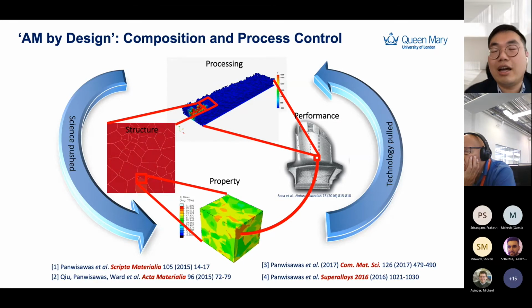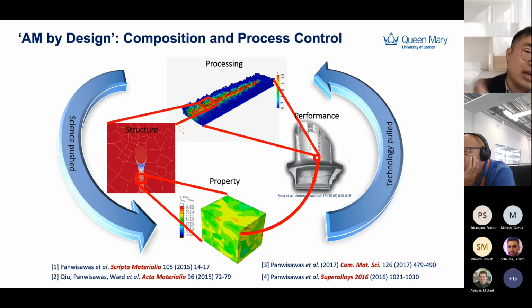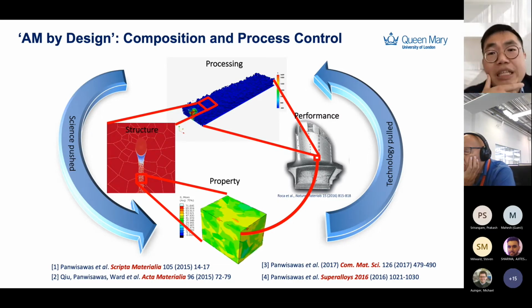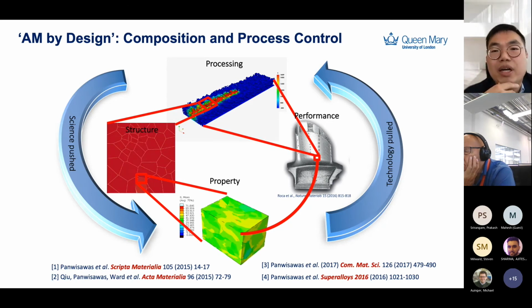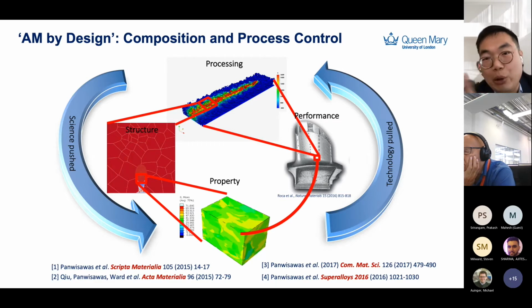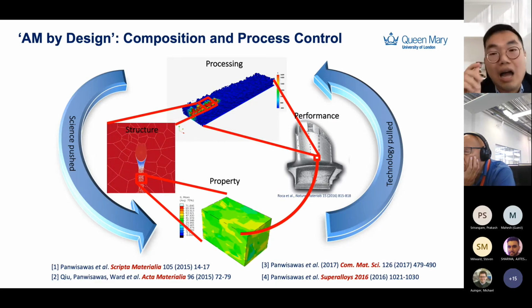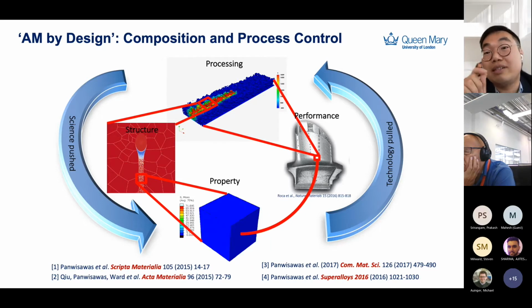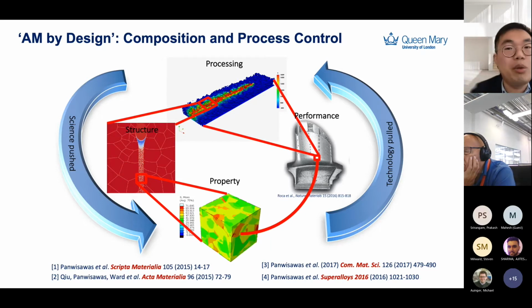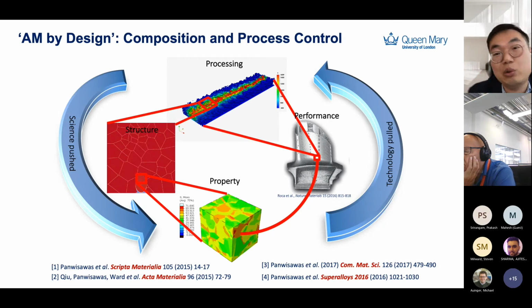That is quite a challenge, because the cooling rate, as I said, the thermal signature in this process is a rapid and repeated cycle, and that makes the microstructure very unstable or non-equilibrium, if you like. And this has to be understood in order for us to decide further the new component or the new property that you want, in order to match at least the traditional manufacturing process.